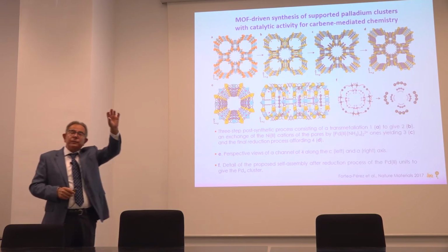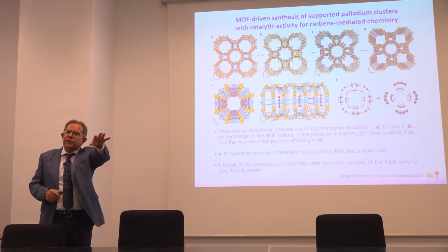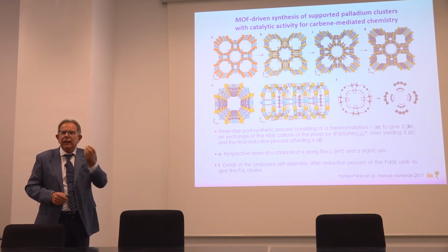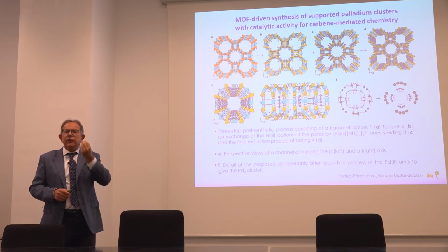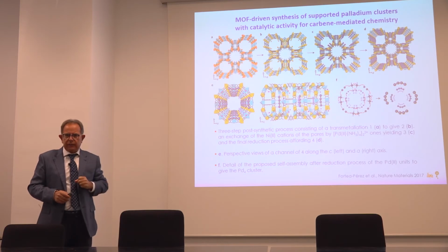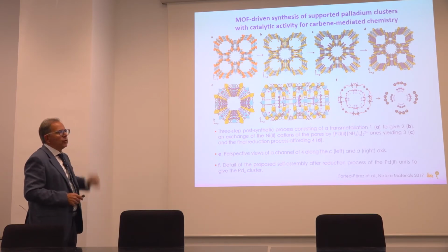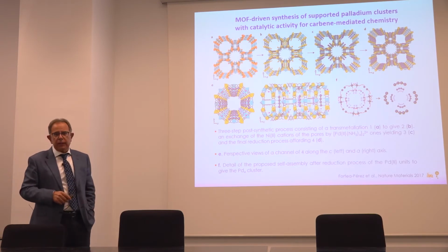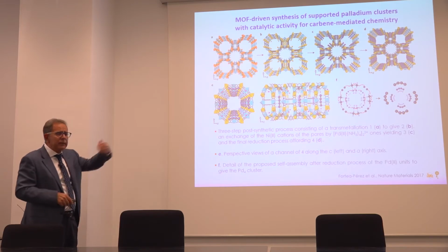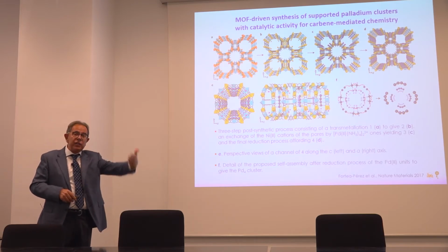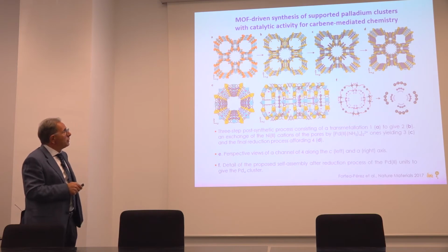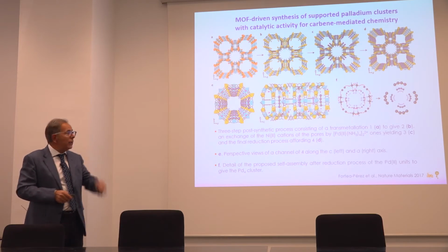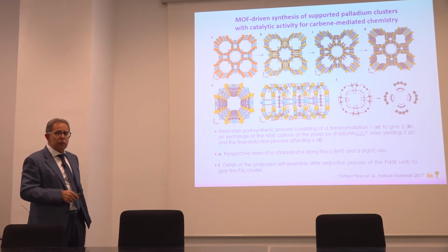You can put sites in the nodes, and you can put sites on the ligands. What about inside? Besides nanoparticles that have been introduced, we thought about the possibility of introducing very well-defined metal clusters. In collaboration with Emilio Pardo from the University of Valencia, we prepared in three steps a MOF by doing a transmetalation, then an exchange and one reduction, to finally obtain, as you see, clusters of four atoms of palladium, very well-defined.